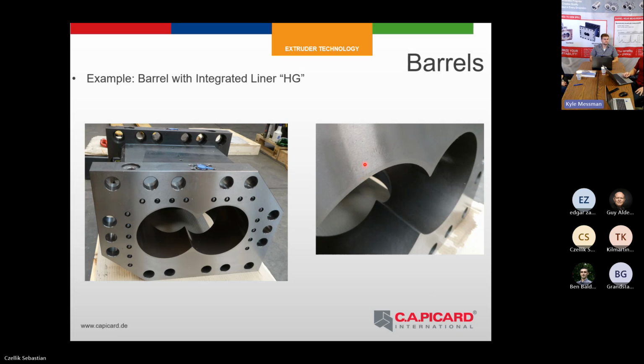The challenge here was not only to make this liner by hipping. There was also a challenge in the hardening of this lining, because, as you can see here, this solid liner is very massive. We have a lot of volume of material. While hardening, as Katharina said, we want a very fast cooling. But when we cool down this barrel, there is a lot of warpage stored in this material. So we had many calls with our heat treatment supplier on how to make this cooling fast enough to get the hardness into this coating.